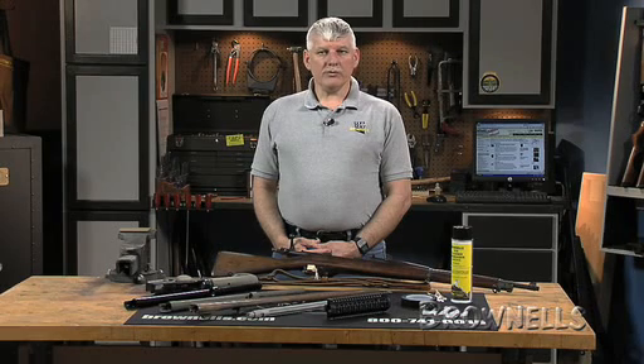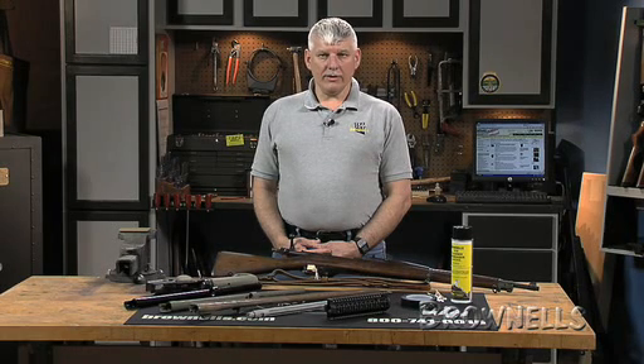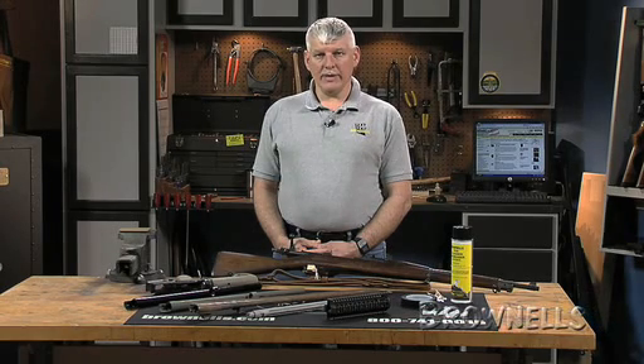Heat at 300 degrees for 20 minutes or blow dry the entire gun with a heat gun or blow dryer before finishing. Remember to degrease with TCE after parkerizing to remove any deposits from the bath. A parkerized finish will result in an excellent surface for spray coating and will give additional corrosion protection, but is not required. Most spray coatings actually give better salt spray protection than bluing or parkerizing, and even some electroplating.